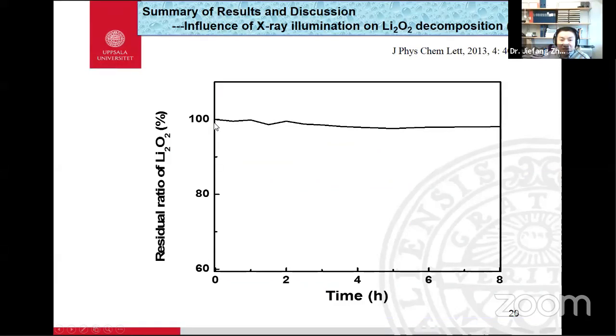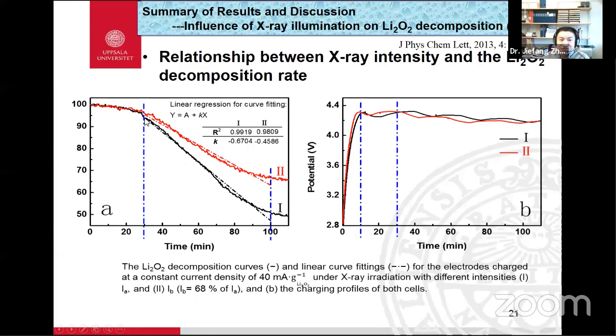But if we put the battery and keep it for 8 hours without X-ray radiation, without charging, which means without the external circuit, then lithium peroxide is quite stable. It keeps the same level after 8 hours. We also found that the acceleration of the decomposition of lithium peroxide is proportional to the X-ray intensity, as you can see here.